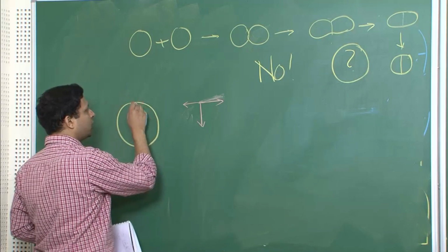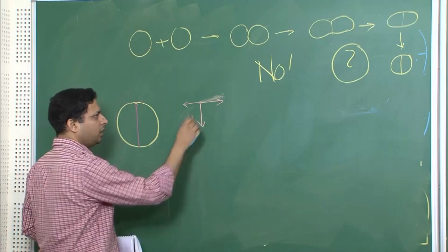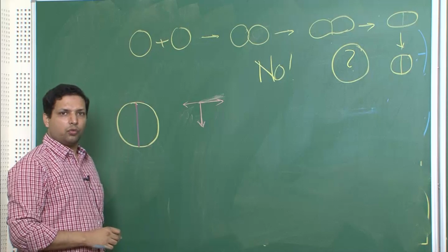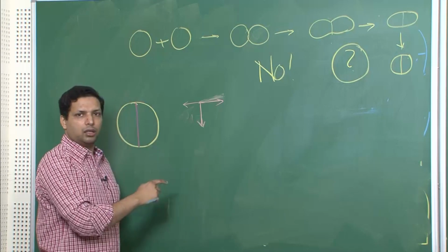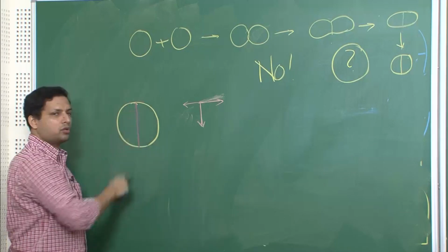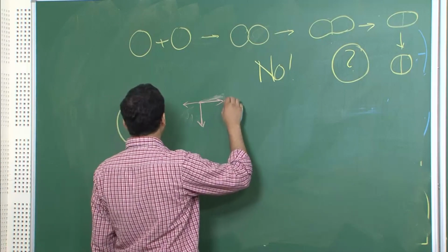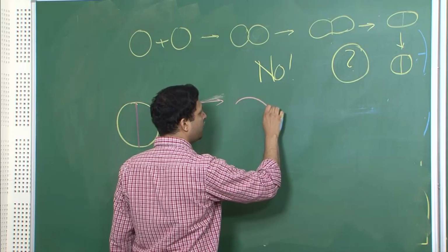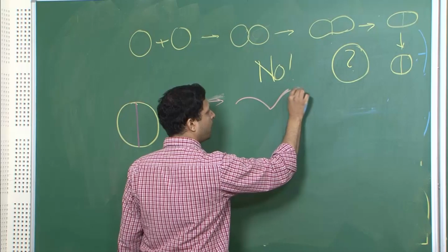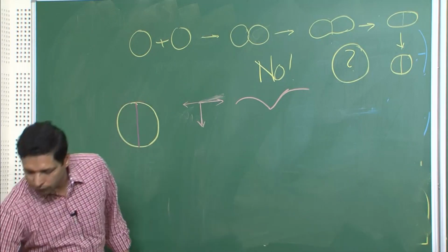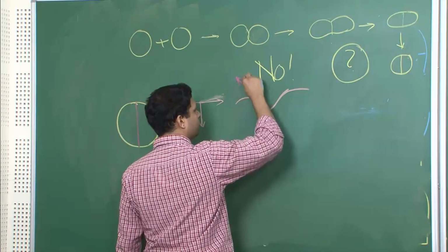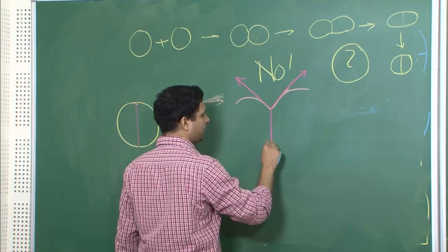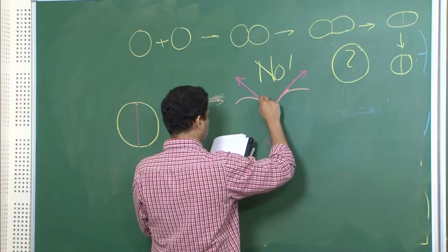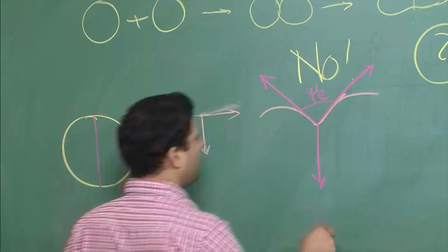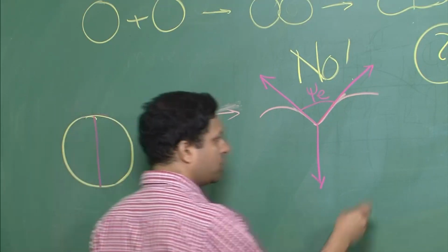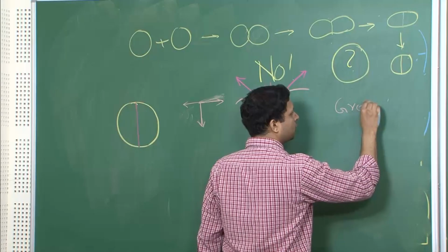Now, you see, if this were the configuration, these two would have been like this, and therefore, this energy is not getting balanced, which would only happen if there were no energy in this, but that is not true. There is some energy associated with grain boundary, and therefore, the actual surface must have a shape like this. So let us call this angle psi E, and this is what is called as grooving, grain boundary grooving.